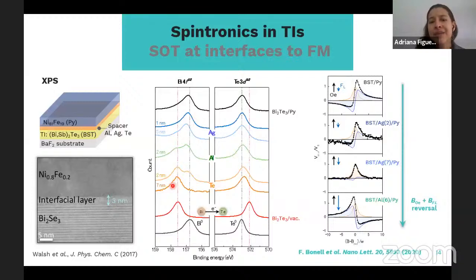Okay. But in terms of spintronics, spin transport and spin to charge interconversion, tellurium is not ideal, because it absorbs too much of the spin current. So you want a metal that allows that spin current to go through and exert the torque onto the permalloy. In that case, we went for aluminum, and we see that with aluminum, we definitely have a component of this field-like torque, which is the one that we are interested in, the one that we want to be more relevant in our measurements. So this is the optimal interface, or the optimal heterostructure, for spin orbit torque in these heterostructures.